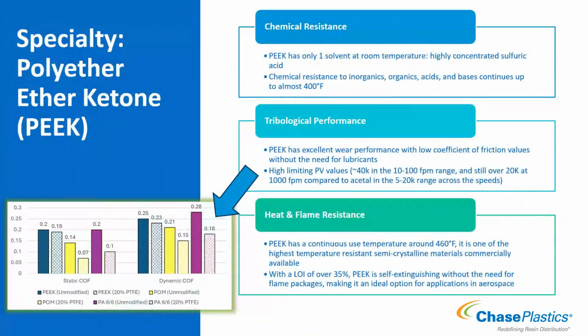Some performance features about PEEK and why you might use it: excellent chemical resistance. Semicrystalline materials tend to have excellent chemical resistance, and PEEK is no exception. It has only one known solvent at room temperature, and that's highly concentrated sulfuric acid, meaning only one chemical is going to dissolve down PEEK at room temperature. All the other really aggressive chemicals do not dissolve down PEEK at room temperature. PEEK maintains good chemical resistance to a lot of different chemicals up to almost 400 degrees F. So sometimes when you're thinking chemical resistance, you also have to think in environment exposure temperature. If it's something that's going to see those chemicals but at a high temperature, we also need to take that into account because it needs to withstand the temperature and also withstand being degraded by the chemical at that temperature. So PEEK can do that: high temperature performance and good chemical resistance at high temperatures.